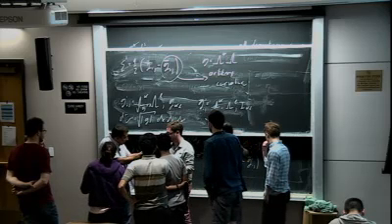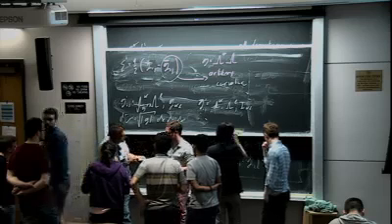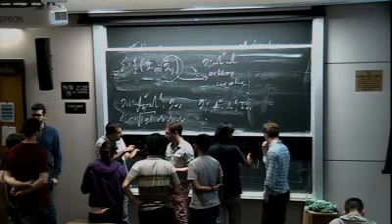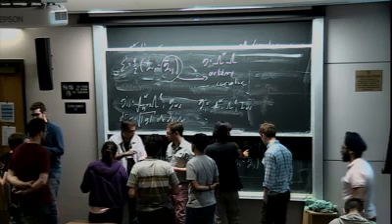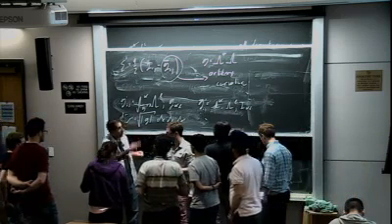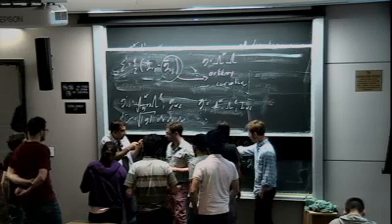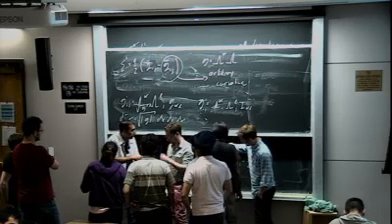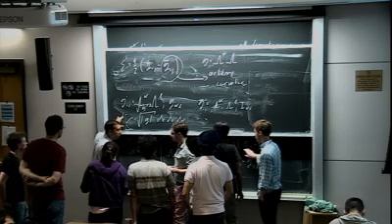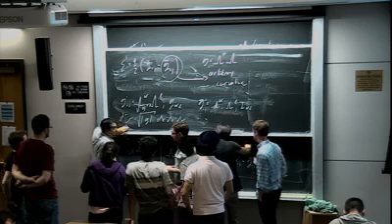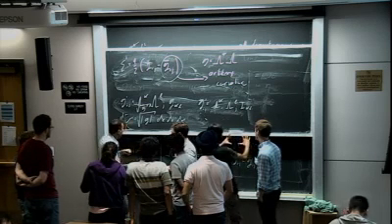Your tension is going to generate a non-Euclidean 2D metric. You would follow these squares. You would see that they hardly deform along this direction, but they differentially elongate along this direction. This was one of the plots David Nelson asked about. You measure distances there as a function of distance from the edge, and you get something that looks like this. The closer you are to the edge, the longer you become. So this is essentially the metric. This is how distance is deformed because of this irreversible deformation.